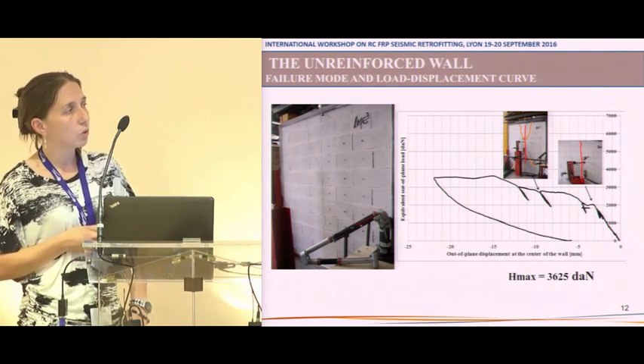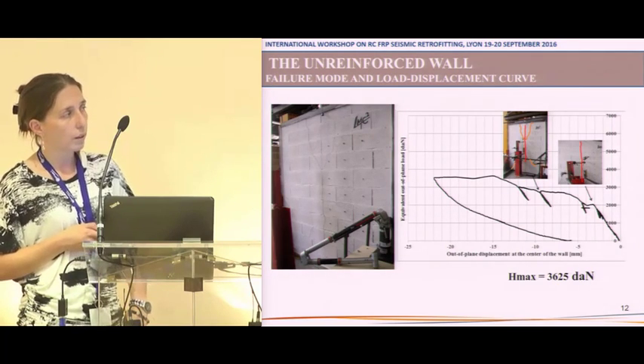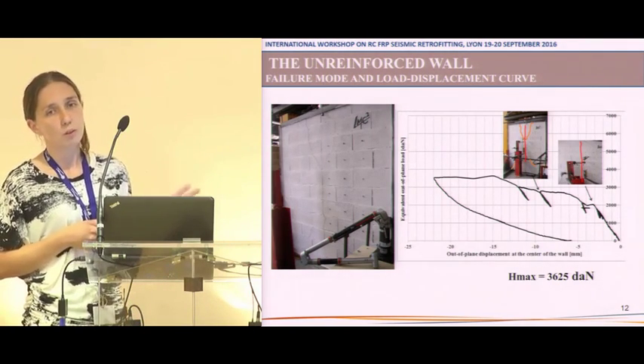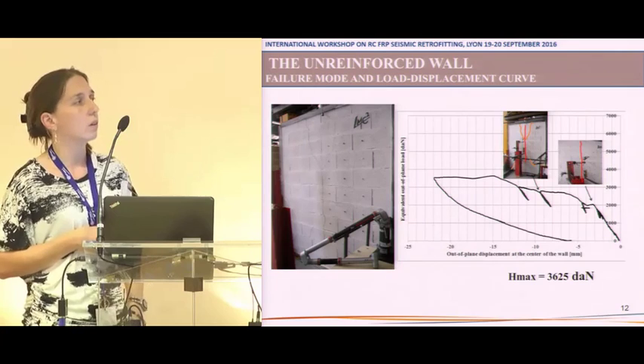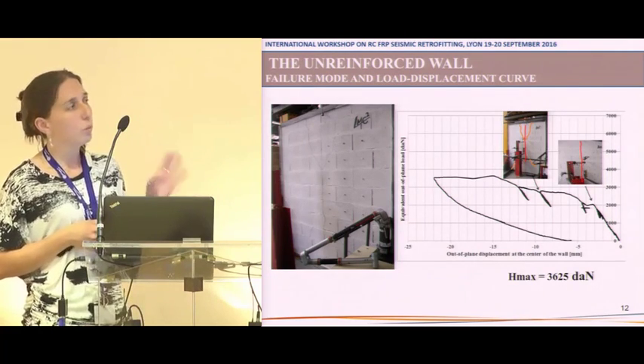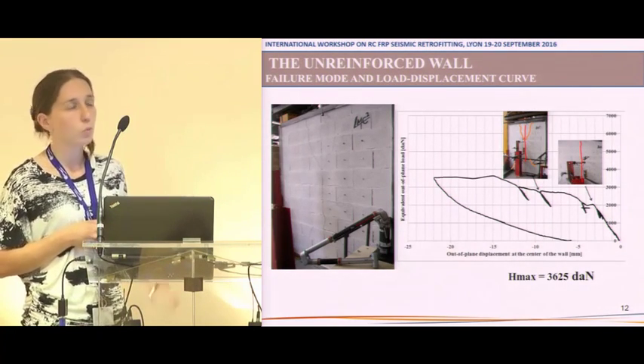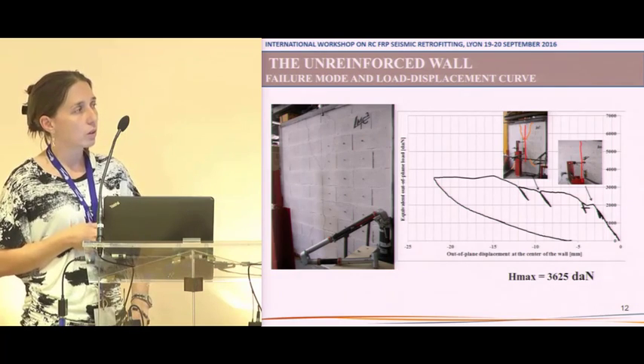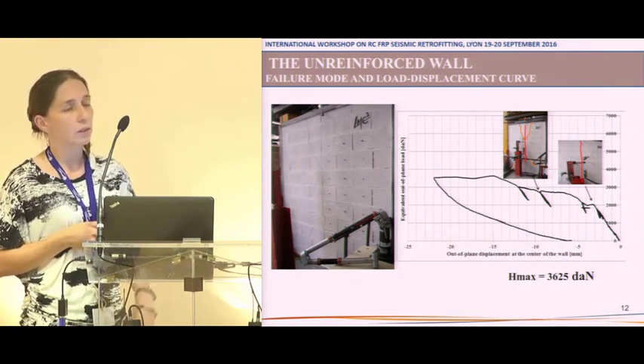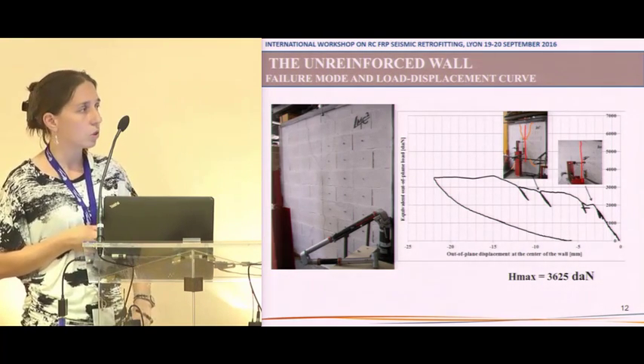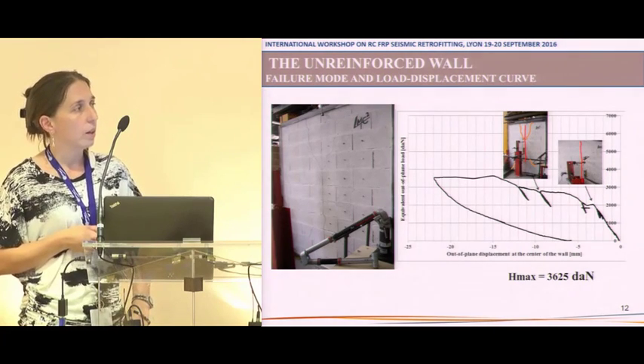It is important to note that the vertical crack progresses through both vertical joints and blocks, and this will be the case for all the tested walls. In all cases, the failures are not concentrated in the joints.